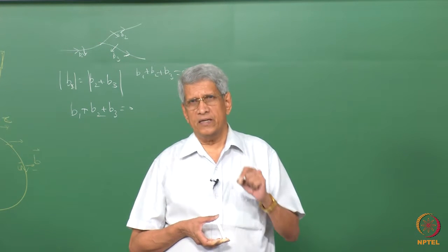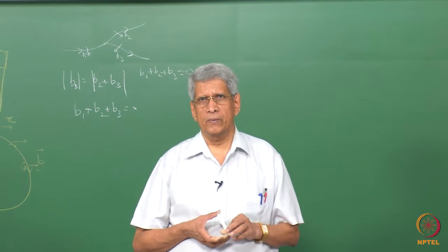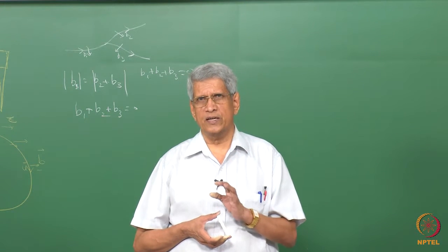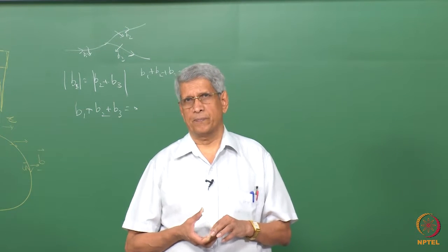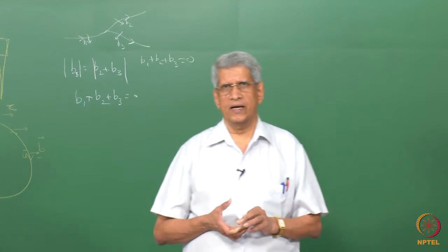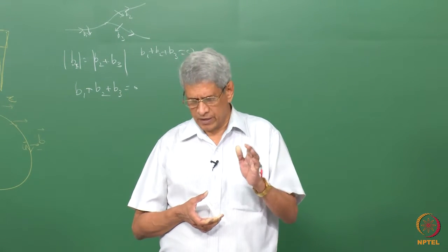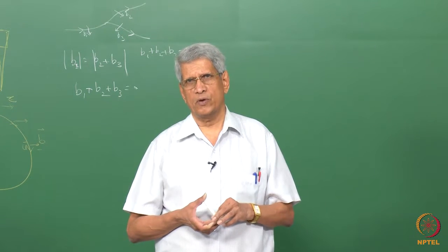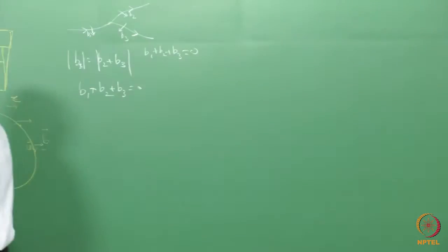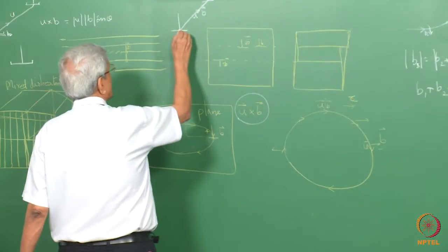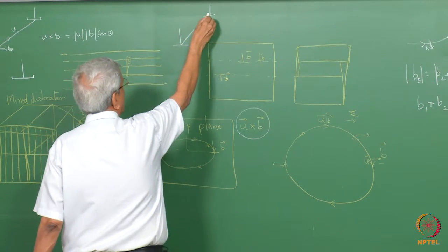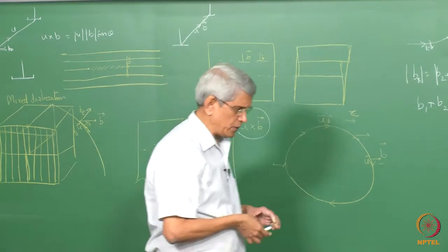The answer is, it is decided by the plane which has got the least frictional resistance to the movement of the dislocation. In the case of FCC material, one plane has got the least frictional resistance to the movement of the dislocation. And especially for FCC material, for a perfect dislocation, two slip planes intersect each other for the same dislocation.